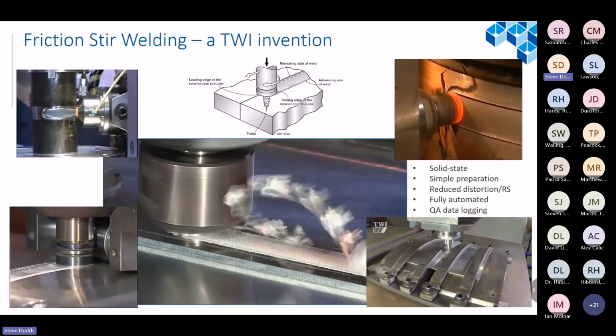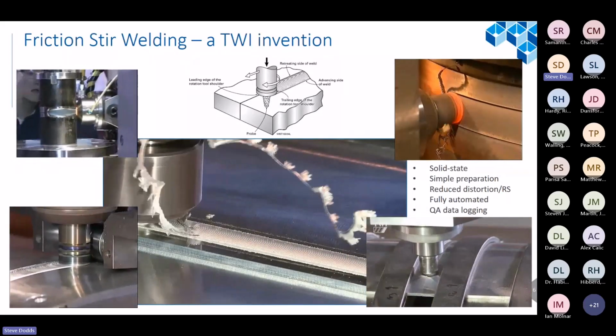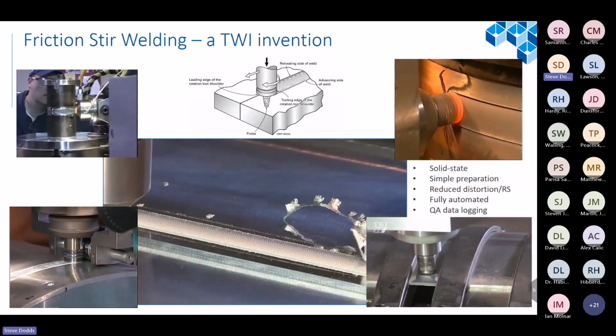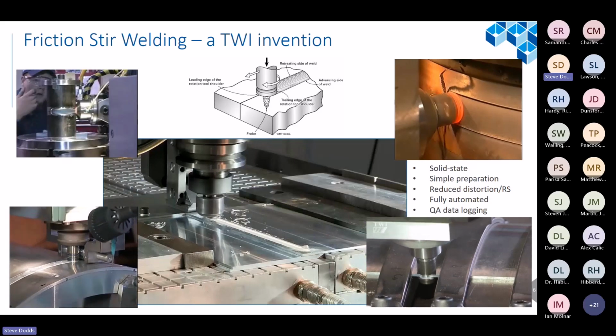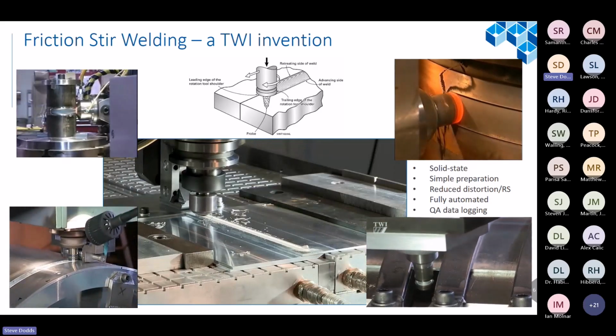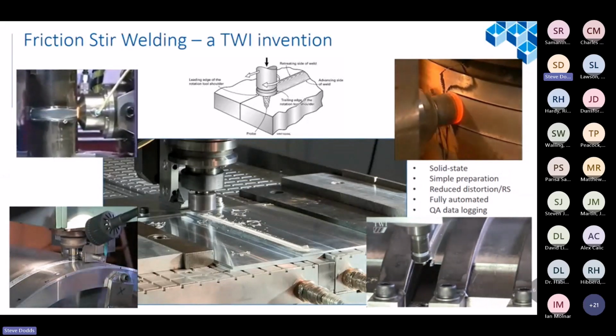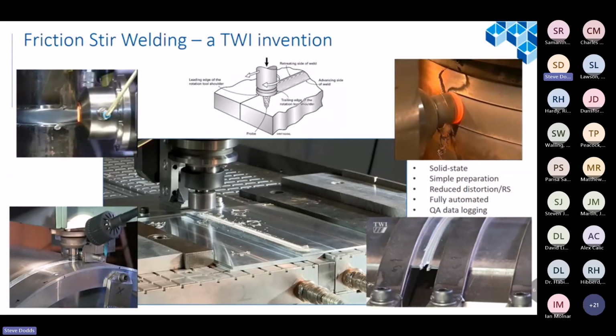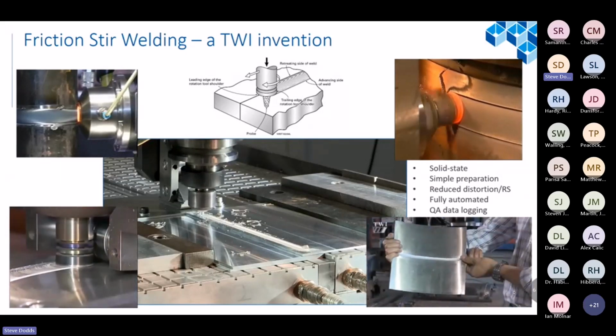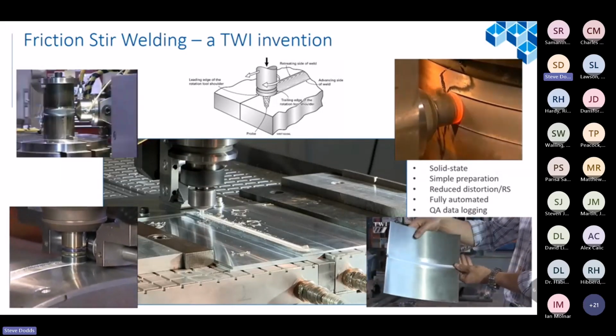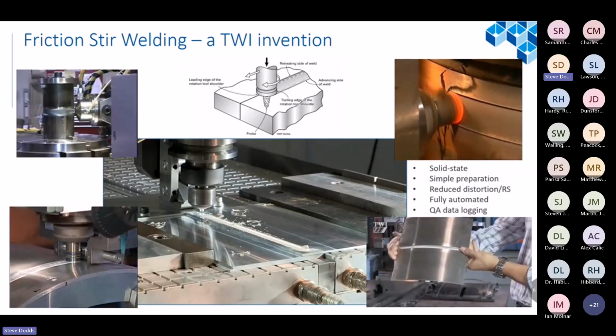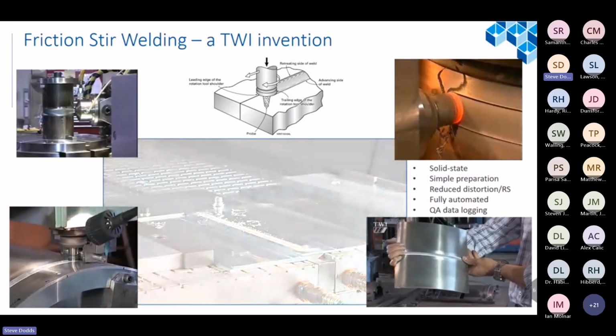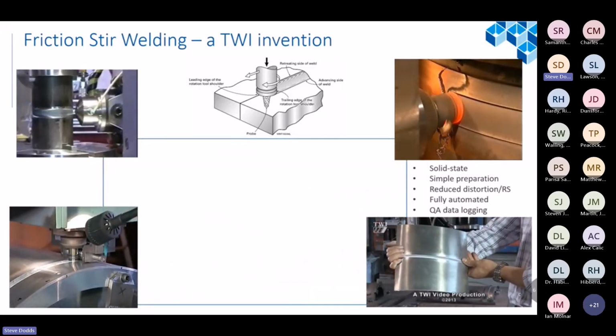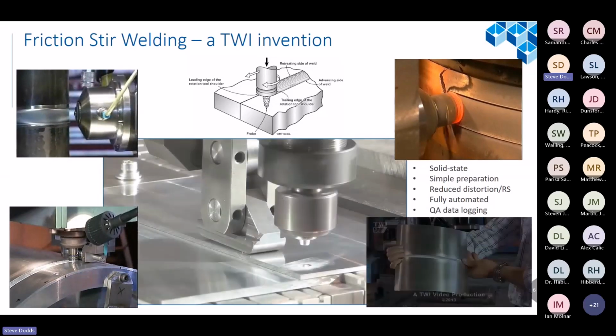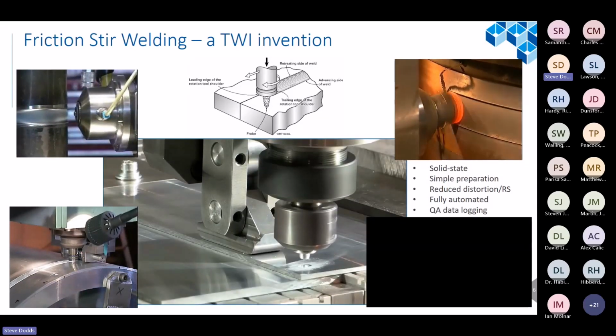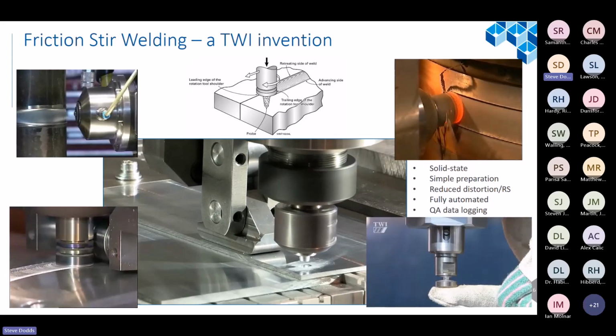Now, the reason friction stir is useful is because it is solid state, so you don't have any welding gravity effects, as you would if you were to go molten. It's very simple preparation. We can work with any straight edge joint. There's no filler involved. Because we're not melting, there's much less heat energy going in, so we're reducing distortion and residual stress. It's fully automated, these are all CNC G-code machines. There's no reason why you can't put a machining head in here as well and trim off the faces. And really useful for this sector, the data is logged for QA, so we can tell exactly what happened in a weld and keep a full weld history.